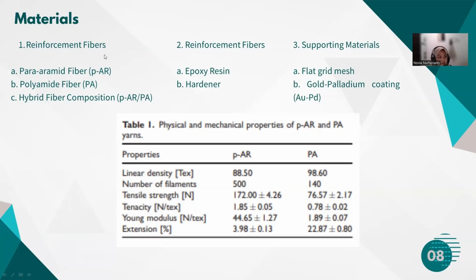Reinforcement fibers: para-aramid fibers, polyamide fiber, hybrid fiber composition. Matrix: epoxy resin and hardener. Number 3, supporting materials: flat grid mesh and gold palladium coating. The physical and mechanical properties can be seen in table number 1.